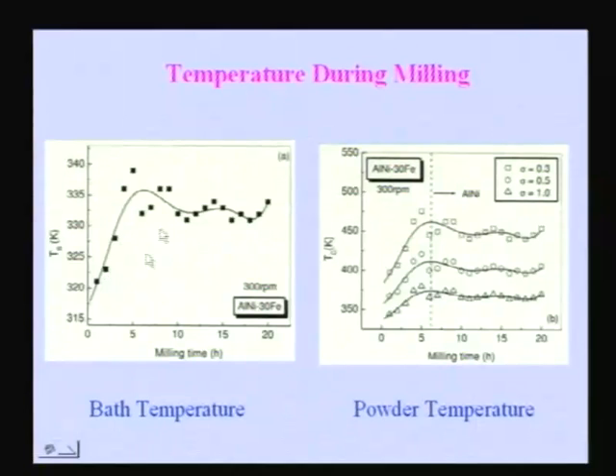So people had a look at that and could see that the temperature never goes beyond about 300 degrees. And we did a lot of modeling and tried to measure the temperature of the toluene bath and tried to have an equation which correlates the actual temperature of the powder to the temperature of the bath, and we could see the temperature never goes beyond 450 Kelvin. 450 Kelvin is about 200 degrees centigrade. So you can never go beyond this. So that is the kind of temperature rise that you can think of. So temperatures are never very high. So everything is happening more or less at room temperature.